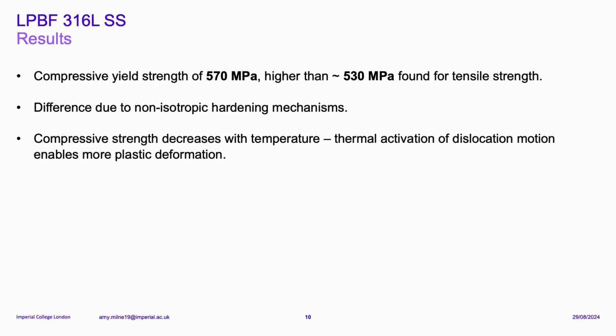So as I just said, the compressive yield strength of 570 megapascals is much higher than that found for tensile strength at room temperature, and the difference is likely due to non-isotropic hardening mechanisms, which I'll talk about in the coming slides. Again, compressive strength decreases with temperature increasing because you've got the activation of dislocation motion, allowing for more plastic deformation.